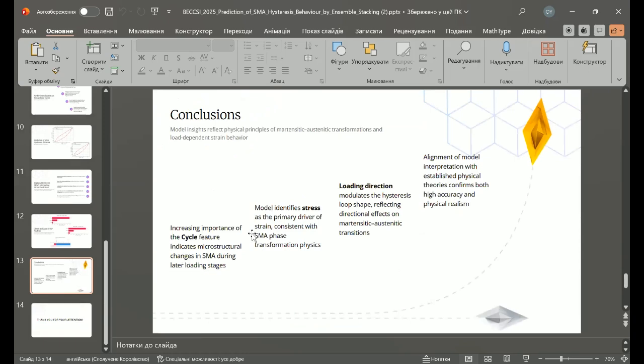Finally, I would like to conclude. Model insights reflect physical principles of martensitic-austenitic transformation and loading-dependent strain behavior. Increasing importance of the cyclic feature indicates microstructural changes in SMA during later loading stages. The model identifies stress as a primary driver of strain, consistent with SMA phase transformation physics. Loading direction manipulates the hysteresis loop shape, reflecting directional effects on the martensitic or austenitic transition. Alignment of model interpretation with established physical theories confirms both high accuracy and physical realism.